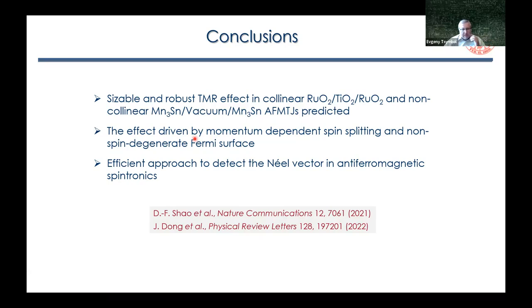So in principle, the answer is yes, unless the domain wall is so thick that you have coherent rotation of the spin. If you have a broad domain wall, in principle this will lead to interface resistance or domain wall resistance, which may be non-zero. So in principle the answer is yes, but likely the effect will be much weaker. But it should be non-zero, ideally.